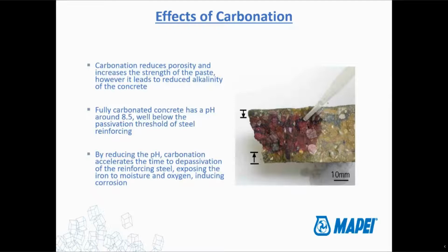So carbonation in and of itself is really not a bad thing. It's not causing deterioration of the concrete. It can lead to some corrosion of the reinforcing steel, but it's more of that really widespread corrosion, like when you're a kid, if you left your bike outside for a couple of weeks and it was just out in that moist air, it starts to rust all over the whole surface of the bike, but it's not like a real bad, penetrating, pitting type of corrosion. That's kind of typical of what we see from carbonation induced corrosion.